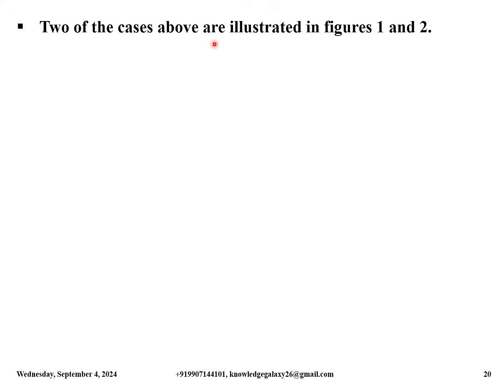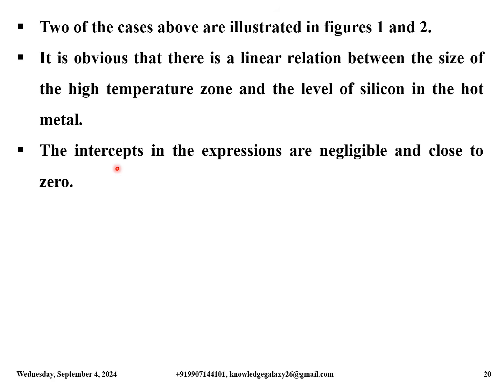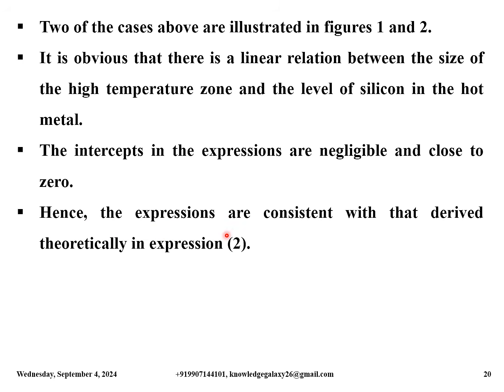Two of the cases above are illustrated in figures 1 and 2, which are coming in the next slide. It is obvious that there is a linear relation between the size of the high temperature zone and the level of silicon in the hot metal. The intercepts in the expressions are negligible and close to 0. Hence, the expressions are consistent with that derived theoretically in expression 2.